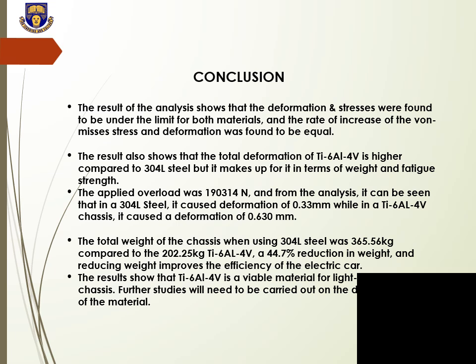It was discovered that the total weight of the chassis frame for the 304L steel was 365.56 kilograms, and that of the titanium alloy was 202.25 kilograms. So we arrived at the conclusion that using a titanium alloy chassis brought about a 44.7% reduction in weight, and a reduction in weight means an improvement in the efficiency and performance of the vehicle. So it shows that the titanium alloy is a viable material for lightweighting of EV chassis. But some further studies need to be carried out in terms of the dynamic